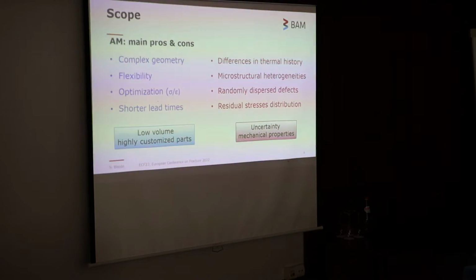Probably all of us are familiar with the benefits and drawbacks of this kind of materials. We know that there are a lot of benefits in terms of complex geometry, flexibility and so on, but we cannot avoid the uncertainty in terms of the mechanical properties, mainly due to the difference in the thermal history along the process. And of course, we need to consider the presence of defects that is not possible to avoid, at least up to now. This also produces different distributions of the residual stresses, which should be taken into account.